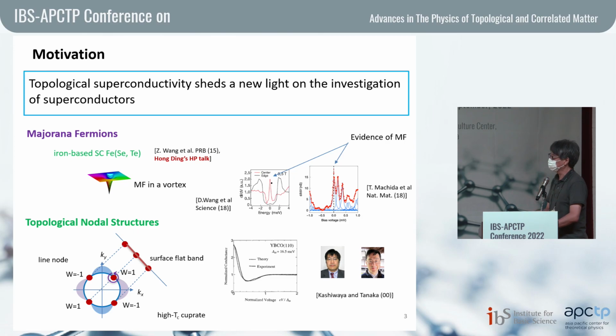As probably all of you know, topological superconductivity shed a new light on the investigation of the superconductors. Actually, we know that Majorana fermion can be realized in various superconductors. And probably the most promising candidate having Majorana zero mode is iron-based superconductors. Actually, this material has a topological insulator nature, so it can support surface Dirac fermions. So in the superconducting state, this surface Dirac fermion can become a topological superconductor. And if you create a vortex in the system, we can expect a Majorana zero mode